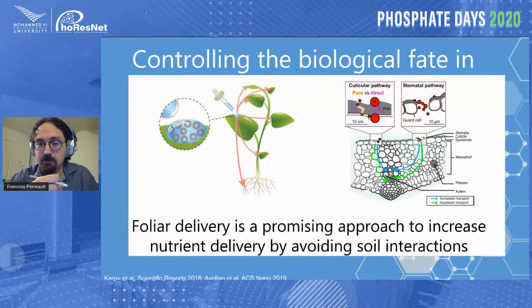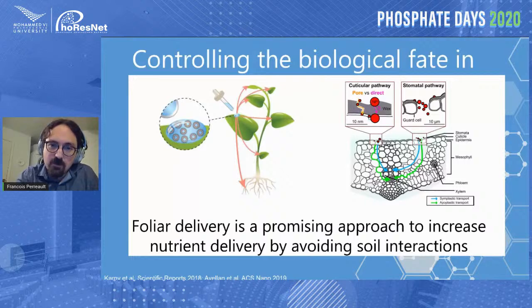What happens when you apply it to the leaf is there is a very interesting size-specific uptake mechanism. Very, very small particles are able to travel into the cracks of the wax layer on the leaf surface. But bigger particles are not able to cross that wax layer as easily. What you can do is enter through the stomatal entry, and there particles up to about 10 micrometers are able to enter easily into the plant.